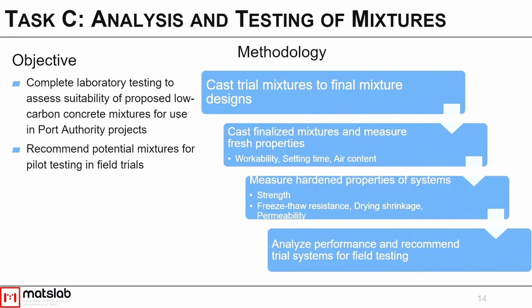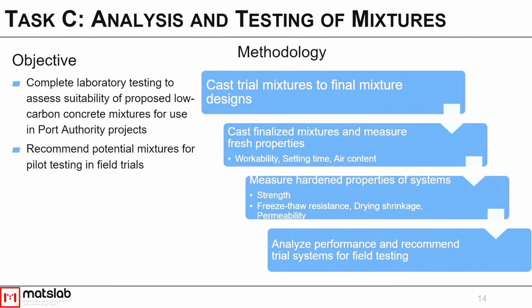We had to do a lot of work with admixture replacement levels and air entrainment levels, things like that, because all of that is very finicky. Those admixtures are so finicky depending on temperature and your exact materials, so that took a little while. And then once we figured those out, we cast our finalized mixtures. We measured fresh properties, so focusing on workability, setting time, and air content. And then we measured our hardened properties, so strength, of course, freeze-thaw performance, shrinkage performance, and permeability performance. And then we analyzed all of those results to come up with potential systems for field testing.